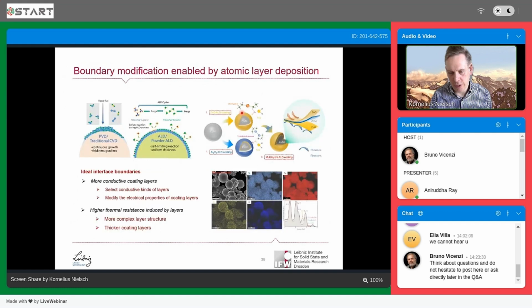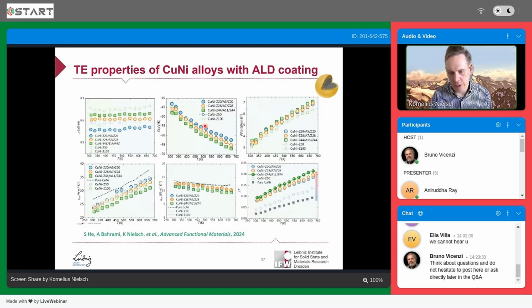At the end, before I come to the end, I also want to briefly mention the application of powder-based ALD. Here we have used just a model system like copper nickel, which we coat with different oxides, for example zinc oxide and aluminum oxide, and we can conformally coat this loose powder before we compact the whole thermoelectric material. And if we apply this powder coating on this model system, we can see that the thermoelectric performance has been significantly improved.